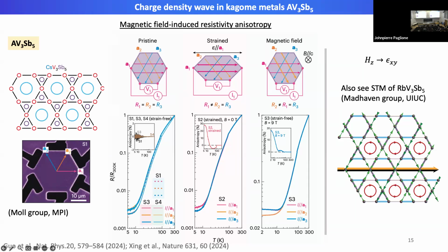At the same time, they are also able to extract the lattice constant change. So the observation is the linearly polarized light-induced charge density pattern change, but it's proposed to come through piezomagnetism: the light induces a lattice deformation, and the lattice deformation, through a piezomagnetic coupling, induces the charge density wave intensity change.